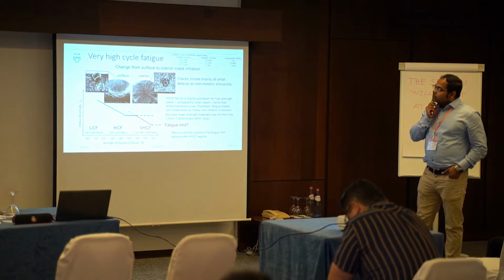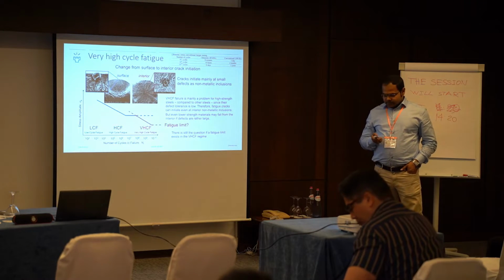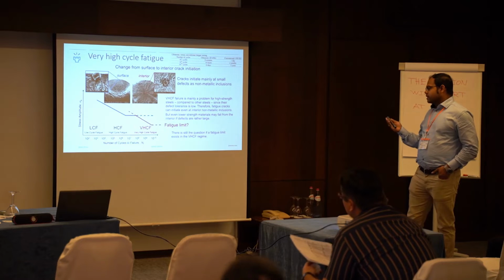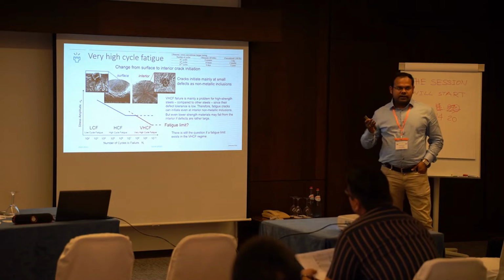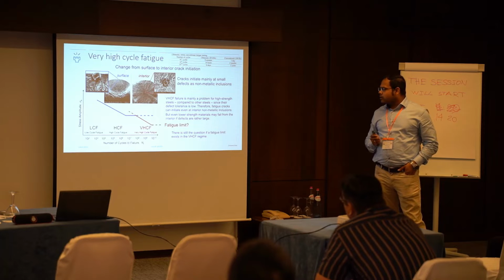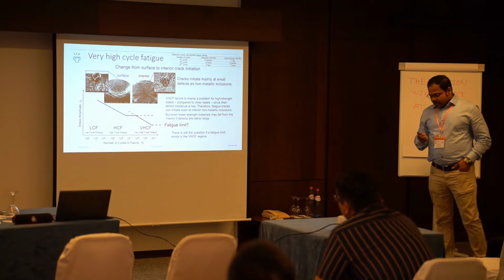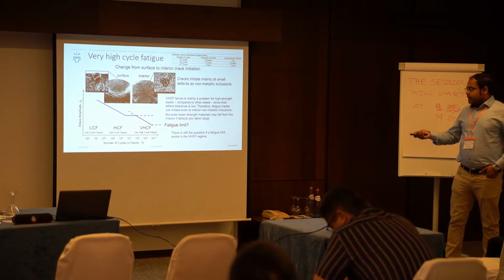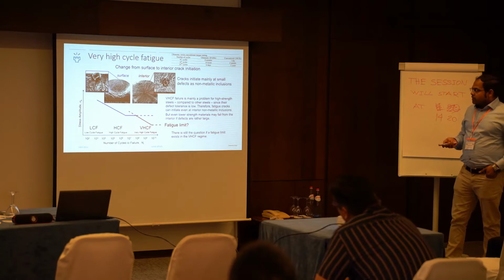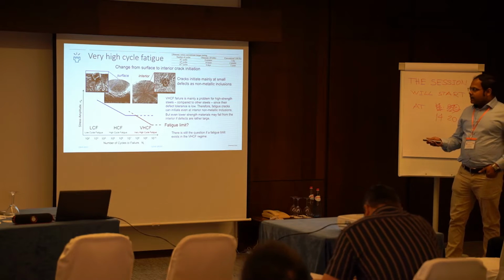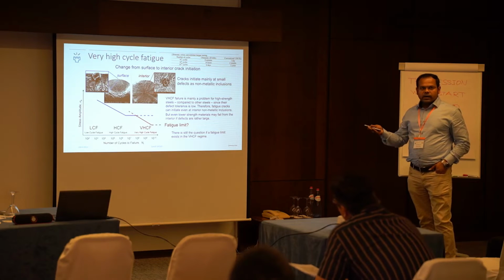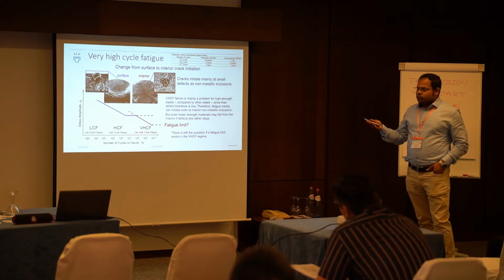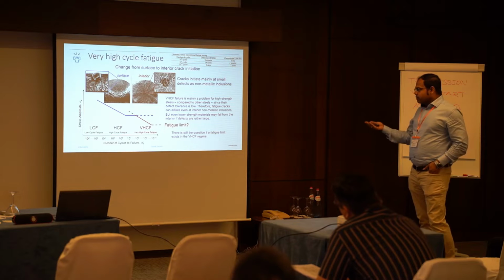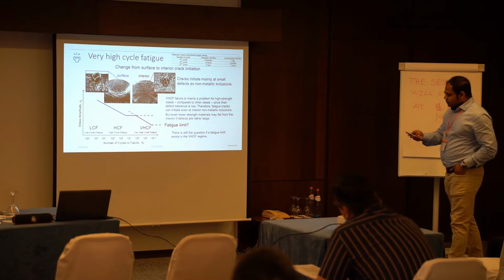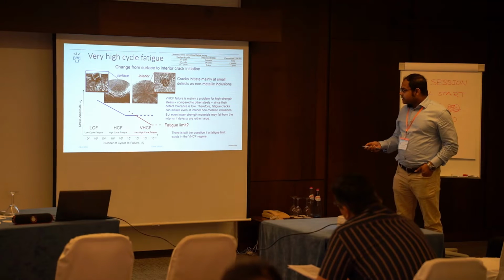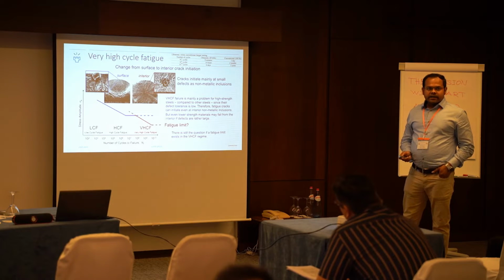So let me quickly summarize what very high cycle fatigue is. If materials survive more than 10^8 cycles till fracture, that typical regime is called the very high cycle regime. And mainly in the case of advanced high strength steel, we observe that the materials fail even at a stress level below the endurance limit obtained through conventional fatigue testing. So now there is a question: does any very high cycle fatigue limit exist or not?